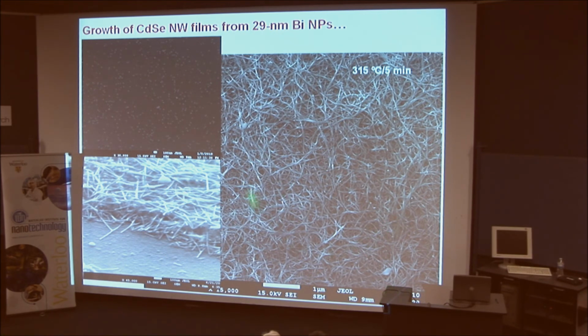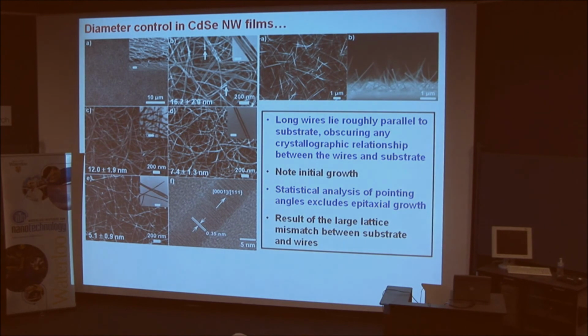Looks like a spaghetti mat of nanowires. Obviously, they don't look nicely vertically oriented. Remember that these wires are dispersible in solvents, so it could be that in the solvent they stand up like this, but the capillary forces, when we just pull them out of the solvent, might cause them to collapse onto the substrate. So this may not be the end of the story. Obviously, I wish I were showing you nicely vertically oriented films, but nonetheless, we can control the diameters of these